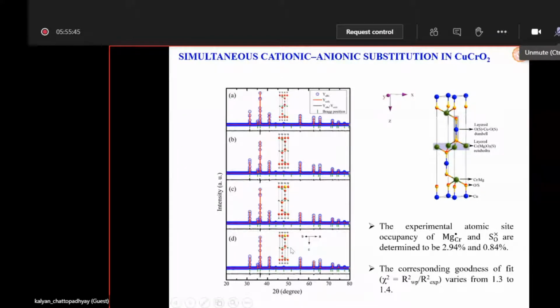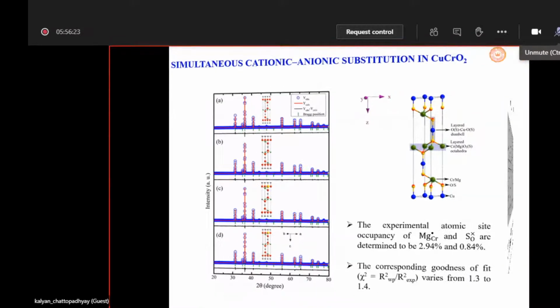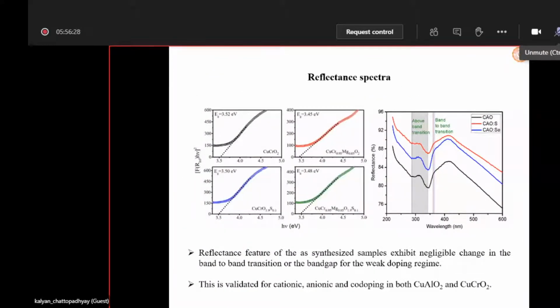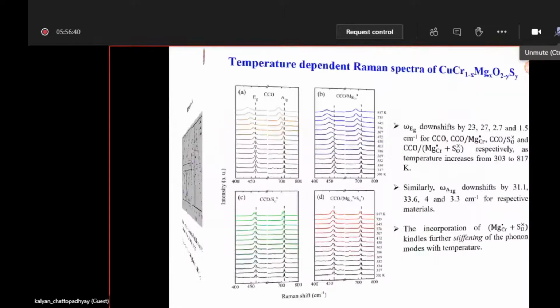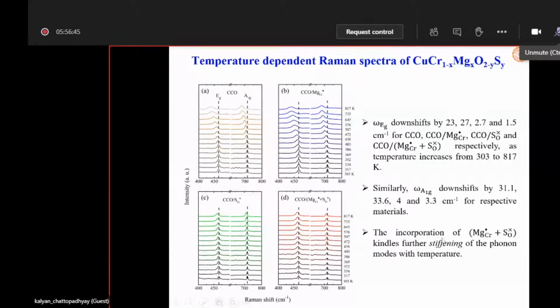For these four kinds of samples, first of all, you have to confirm that the correct phase formation has really taken place, so we performed a detailed Rietveld analysis, and you see that the fitting is very good, with chi-square about 1.3 to 1.4, which is an extremely good fit for this complex system. We can also quantify the doping. For example, the magnesium doping percentage is 2.94 and the sulfur doping is 0.84 percent, which can be obtained from the Rietveld analysis, as you know. Now, the interesting point is that these are optically transparent, as can be found from the optical UV spectroscopy. You can calculate the band gap, which satisfies the criterion that it must be greater than 3.1 electron volts.